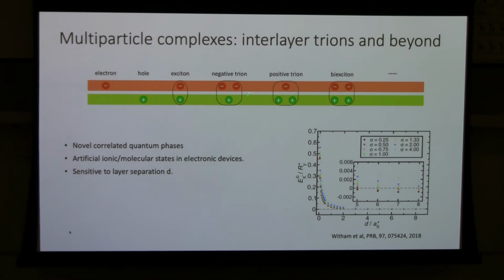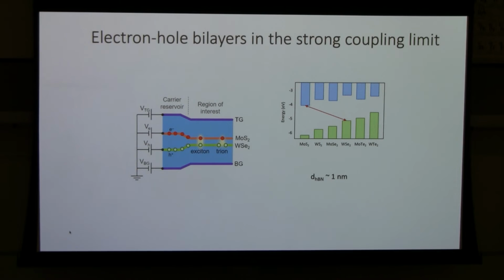If you look at the trion, the behavior is actually different. If you increase the layer separation, the attractive interaction between positive and negative charge decreases. But the repulsive interaction between these two adjacent electrons doesn't change as much. As a result, the trion is much more sensitive to the layer-layer separation. And indeed, theoretical prediction shows that the trion binding energy decreases very quickly. Also, above a critical separation, the trion simply cannot exist anymore. So with that in mind, if we want to study the trion, we know what we need to do is make the distance as small as possible.